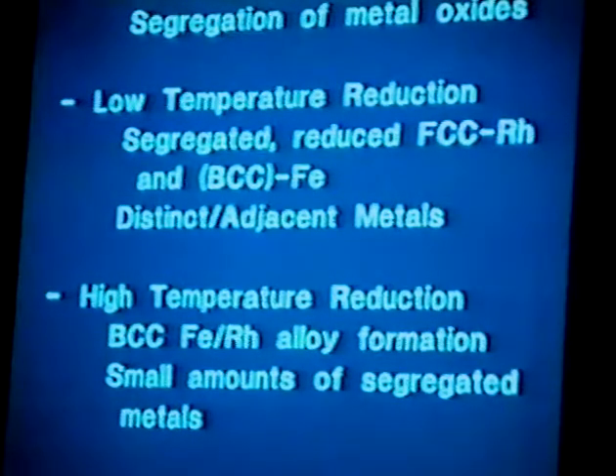If you then take these segregated oxide catalysts and reduce them at low temperature in hydrogen, typically around 100 degrees, what you end up forming is a catalyst that was basically 100% reduced. All the metal was in a zero valence state, but the segregated zones retained their integrity. And so we ended up with segregated gamma rhodium and alpha iron particles inside larger agglomerates. It was apparent that we had distinct but very adjacent different types of metal particles. And after the high temperature reduction step, which is typically a 400 degree hydrogen treatment, we ended up with a BCC uniform, stoichiometric alloy particle.